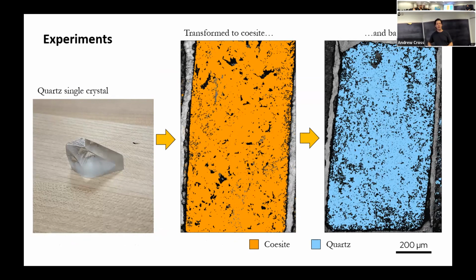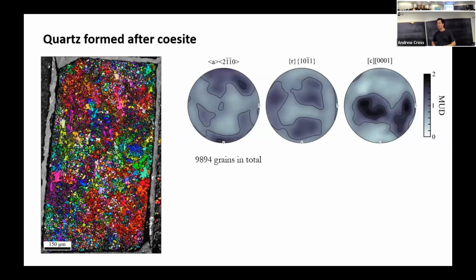So there's a particular crystallographic signature here that people have found in natural rocks. We wanted to see if we could find that in our experimental rocks. So what we did is take a quartz single crystal, transform it to coesite and quench it. That's our starting reference material in this case. And then we did another experiment where we transformed it to coesite and then brought it back to quartz. You can see after the experiment, we've taken a single crystal and turned it into about 10,000 grains. So we've got a lot of grain size reduction.